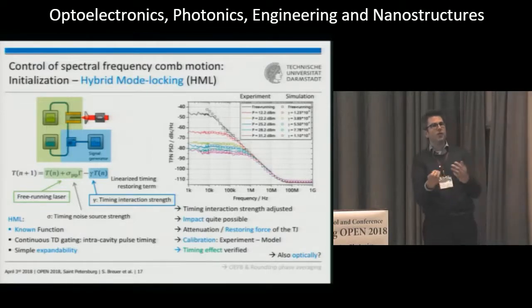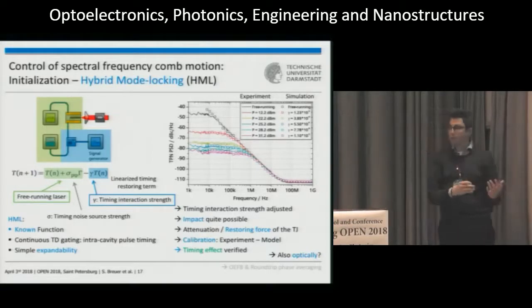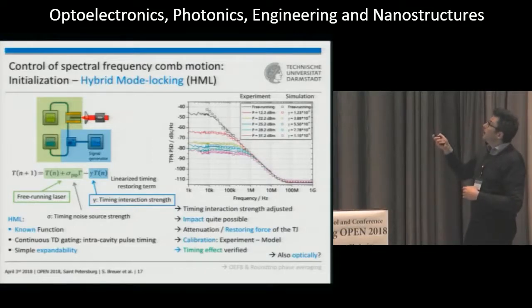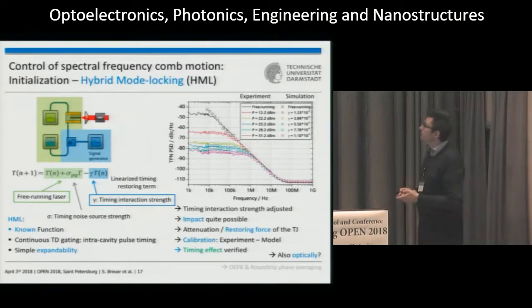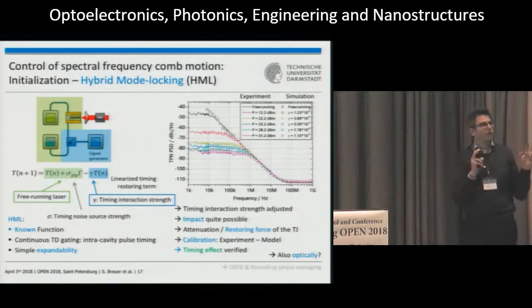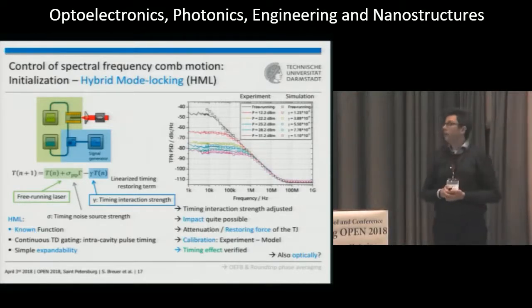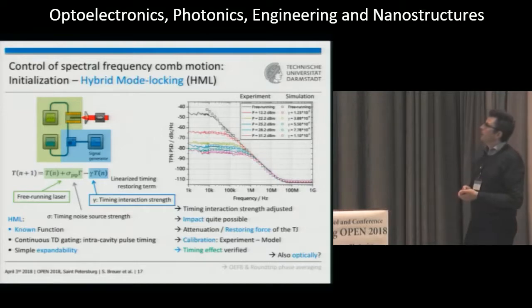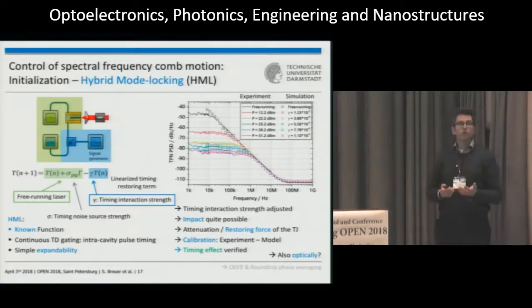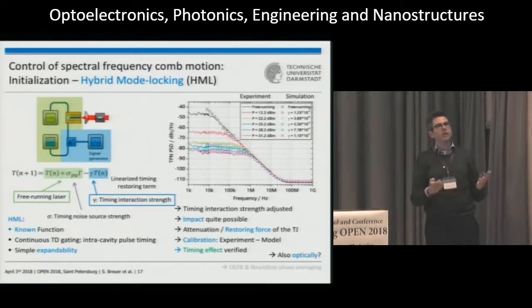It changes for every semiconductor laser, for every active material. We need to adapt this, but it can be nicely done. And once it's adapted, you can find quite a nice correspondence. So we see the impact, and it can serve as a kind of calibration for the measurement. What we can see is that there's a timing effect verified by this approach. The question, of course, is what happens if we investigate the all-optical feedback.